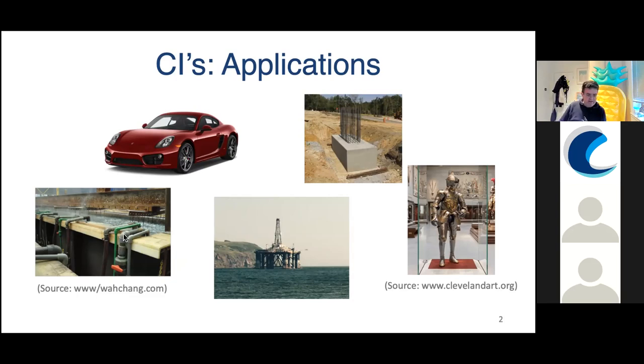So here on the left-hand side, this is an acid bath for removing mill scale from metal sheets before going on for painting and processing. And here, the acid bath, which is highly concentrated sulfuric acid, is inhibited to prevent the corrosion of the metal. And also in more unexpected areas, you might find them. So for example, in museums, there might be a corrosion inhibitor, either what's called a vapor phase inhibitor or applied as a wax, for instance, to this suit of armor.